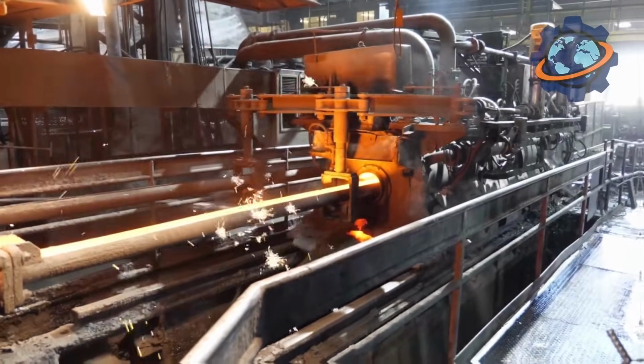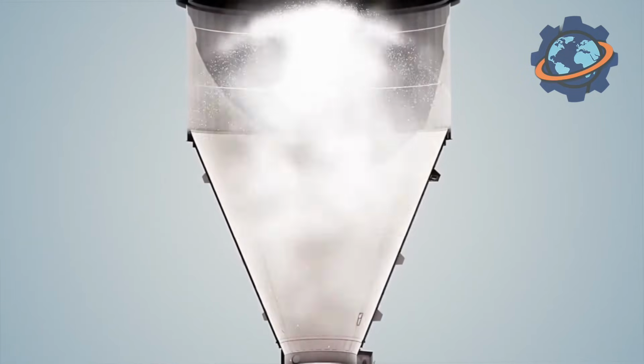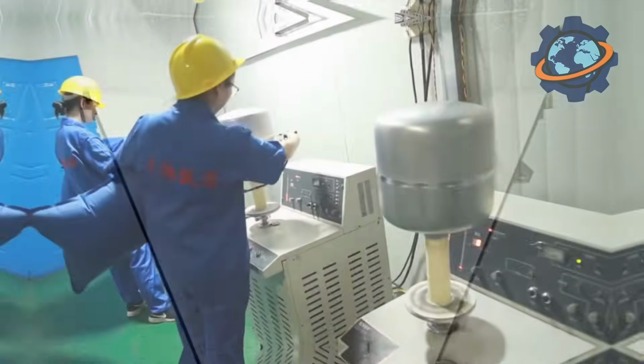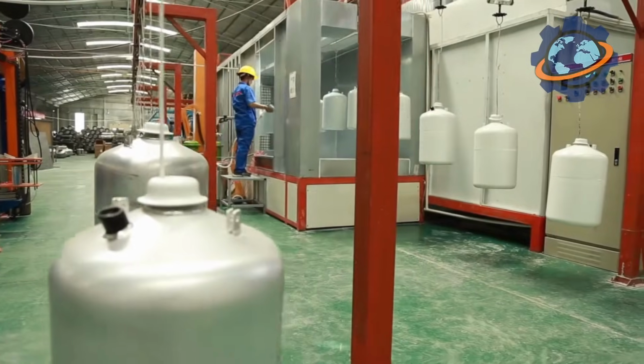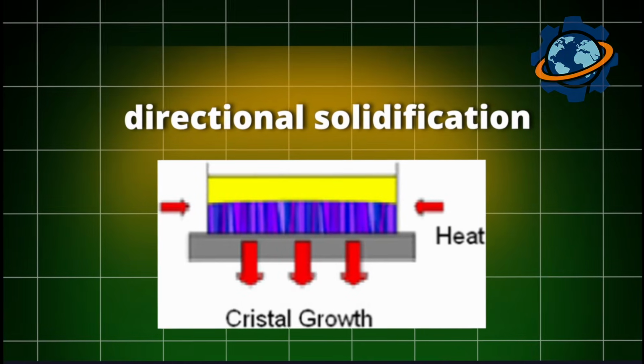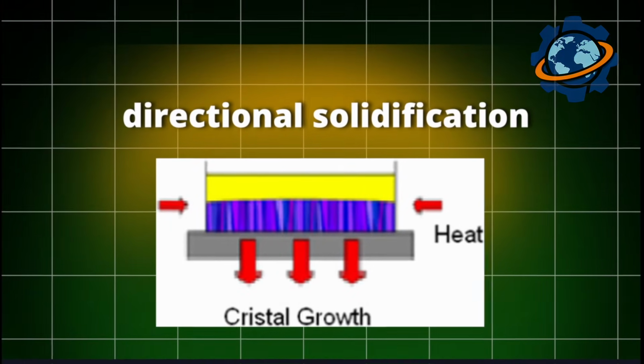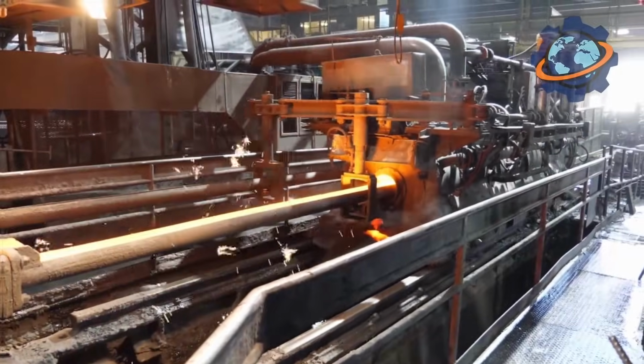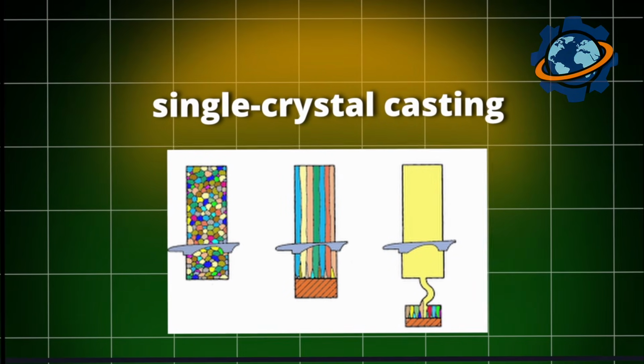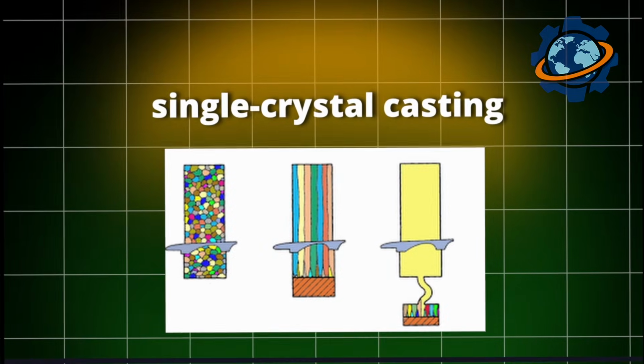The breakthrough came when Pratt & Whitney researcher Francis VerSnyder invented directional solidification in 1966, eliminating transverse grain boundaries and doubling blade life overnight. The true revolution arrived in 1982 when General Electric and Pratt & Whitney independently perfected single crystal casting. Turbine inlet temperatures jumped from 2,000 degrees to 3,000 degrees Fahrenheit, a 50% increase enabling massive efficiency gains. Modern turbofan engines achieve fuel efficiency triple that of 1960s designs.